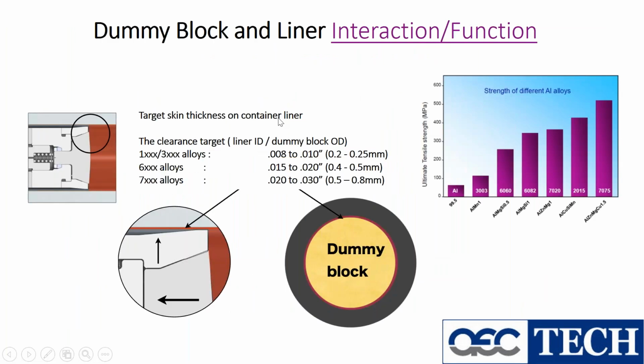Now, when we look at the dummy block's interaction with the liner, this is very critical. And as we fly around and we all move around and we see extruders that are moving from 3,000 to 5,000 to 6,000, even to alloys into the 6082 or 7,000 or 7B04, some of these high tensile, high iron alloys, it's all about extrudability. And by extrudability, we mean the size of the gap in which the alloy can be extruded.